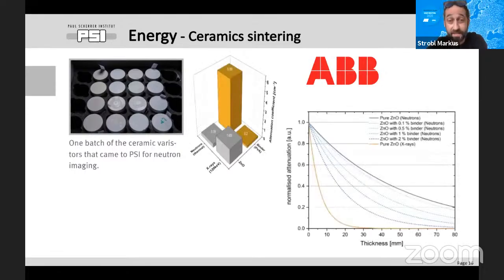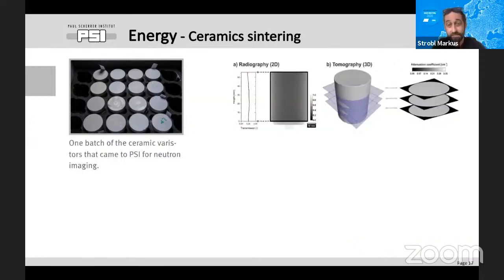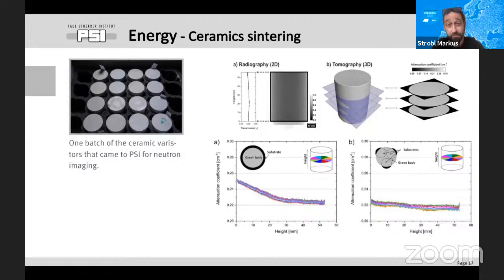So they wanted to know if we can see the binder content, and we first looked into the numbers, and we found that we can do this. And for this work, we also got some support from a little industry funding to do this first project. And we did these investigations, and we helped ABB to optimize their burning in the oven so that they could get rid of the binder material to a level where it doesn't impact the quality.